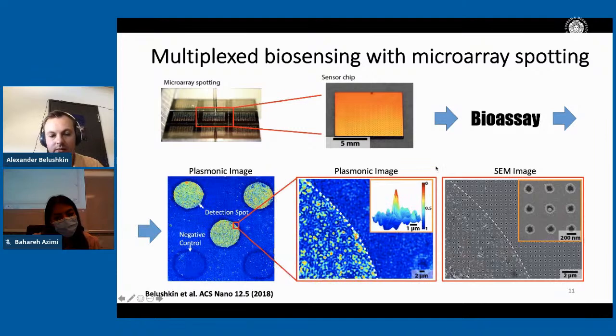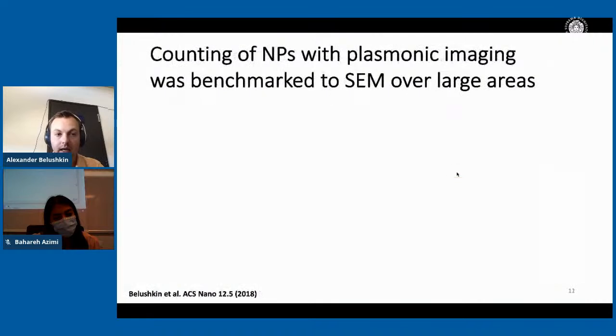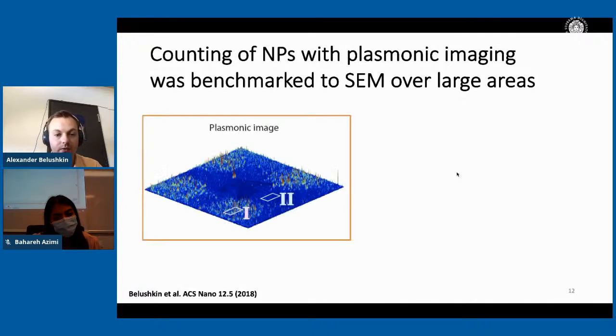But the question still arises: are they really nanoparticles? Can we see all of the nanoparticles that bind, or maybe not all of them? And how does this work? In order to answer that, we took the plasmonic image and benchmarked it to SEM imaging, basically scanning electron micrographs of identical areas. We counted the nanoparticles with the SEM and on the plasmonic image, and we compared them basically 1-to-1 over different areas.